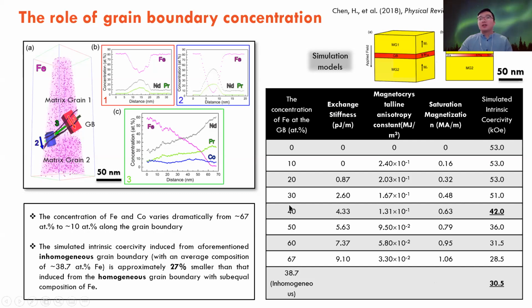What we found interesting here is that, even if the iron concentration is the same at the grain boundary, if the iron distribution is not uniform along the grain boundary, the coercivity is quite a bit lower than for a homogeneous grain boundary, around 27% lower. This is quite interesting, and it will form some guidelines for manufacturers on how to more accurately control the ferromagnetic distributions at the grain boundaries.